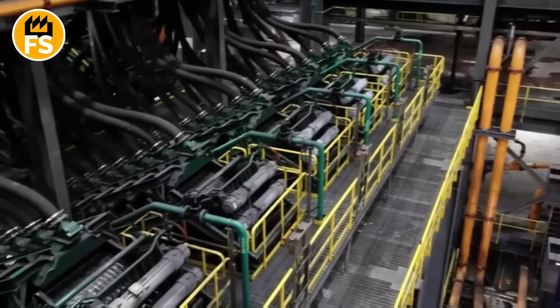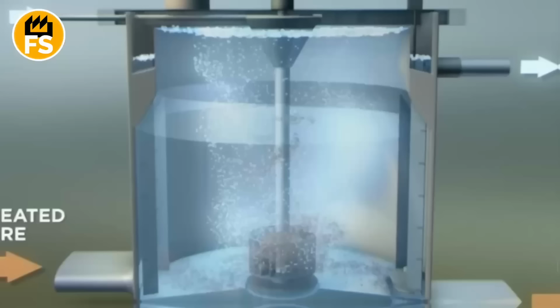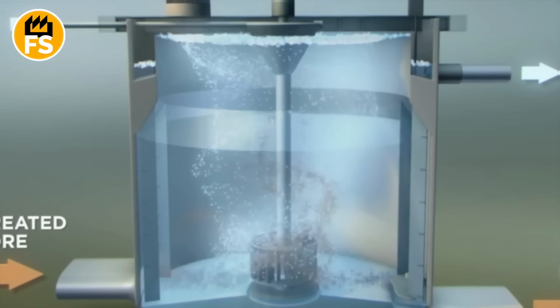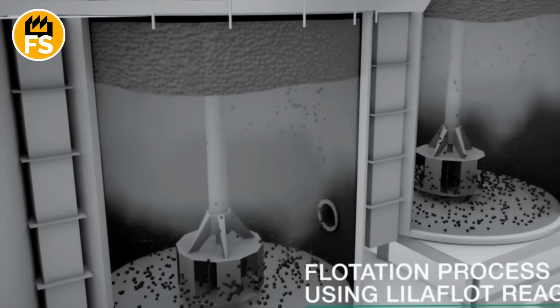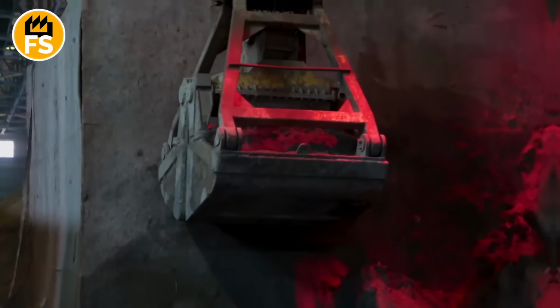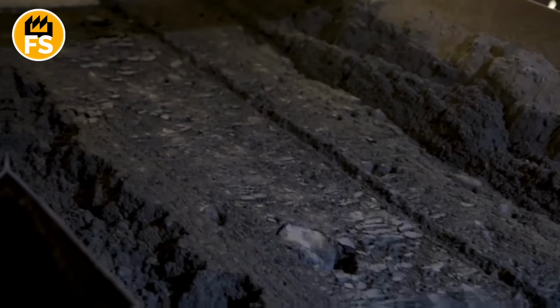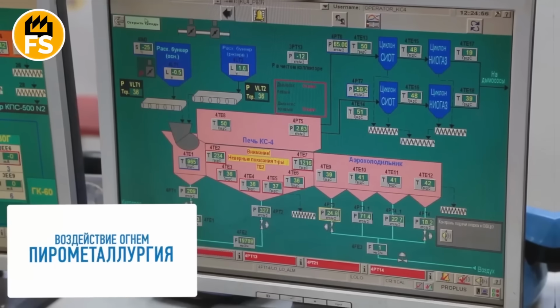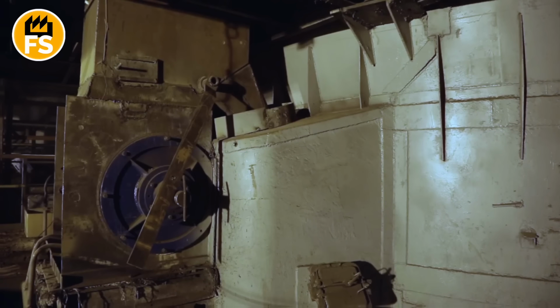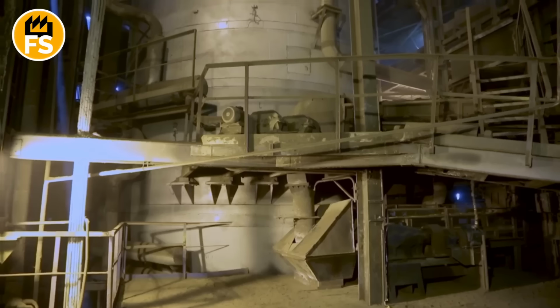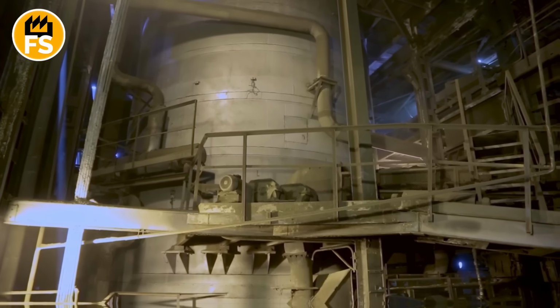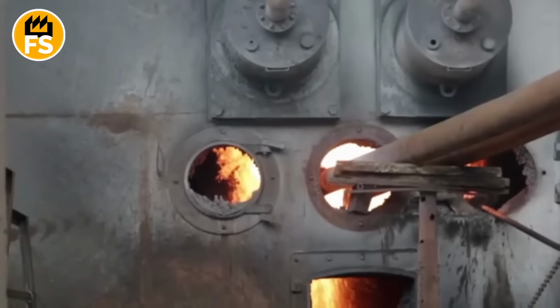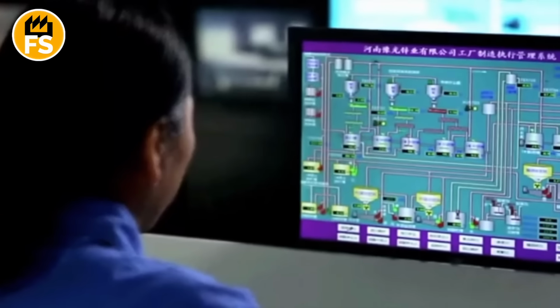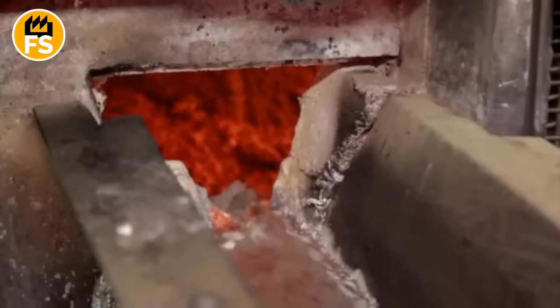Since zinc often hangs out with lead, the plant might run several flotation cycles to separately pull out zinc concentrate from lead concentrate. The zinc concentrate you get, it's still not pure metal. It's got to go through metallurgical processing to turn into actual metallic zinc. And this is where we enter the world of extreme temperatures. If they're using the pyrometallurgical method, the zinc concentrate first gets roasted. The concentrate is heated in special furnaces at around 1,800 degrees Fahrenheit. This burns off the sulfur that's part of the sulfide ore, converting it into zinc oxide.